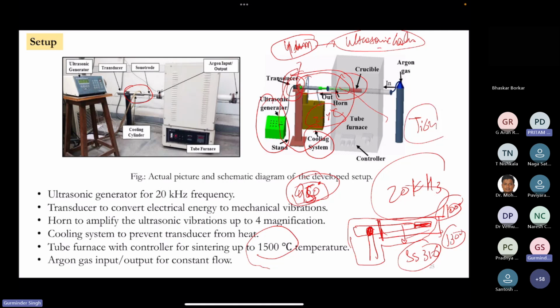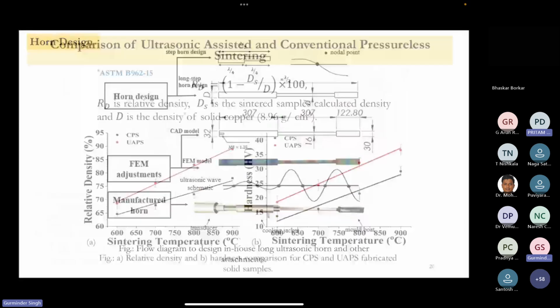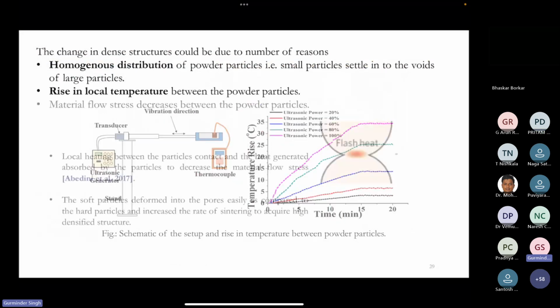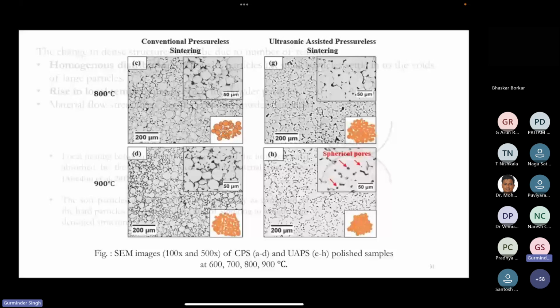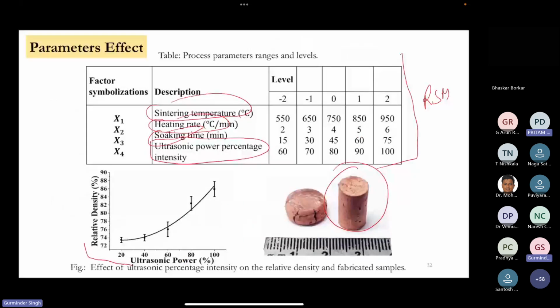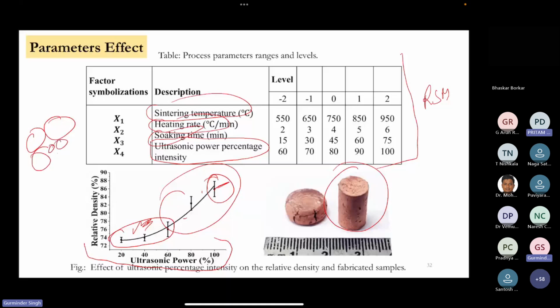Is variation of sonication required for this process or not? We have done it, but 100% vibration always gives you higher results. This is a variation of ultrasonic power. We have done it from 20% to 60%. There was not much change in density, but from 60 to 100 there was higher density, and 100 was giving efficient results. In the error bar also, if you see the 60% power, there is a huge variation, because you can't have the same particle size in every part. It will always have a difference.